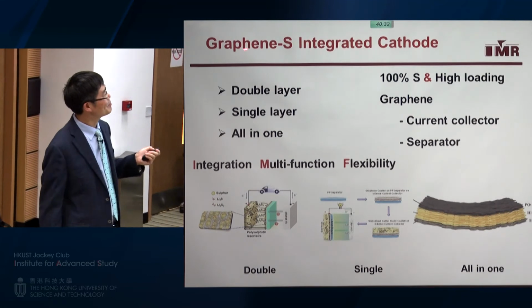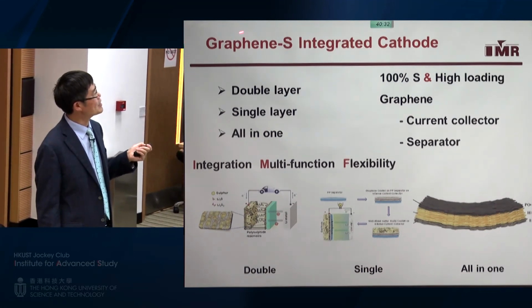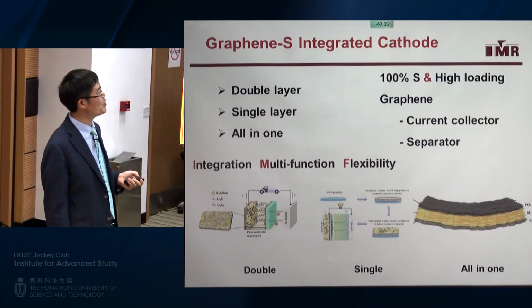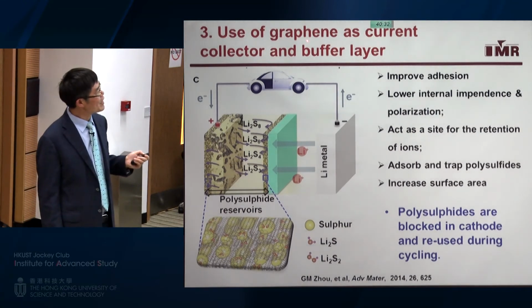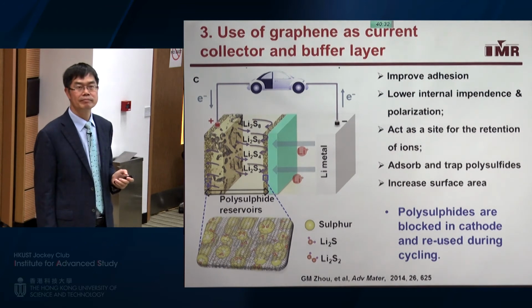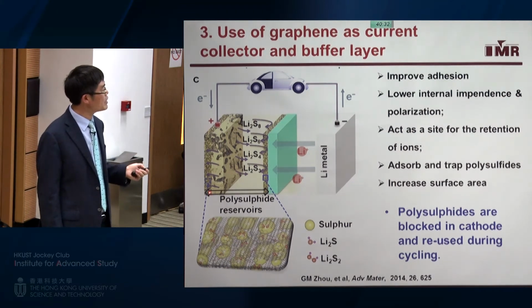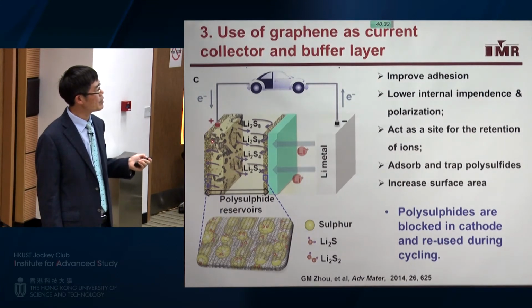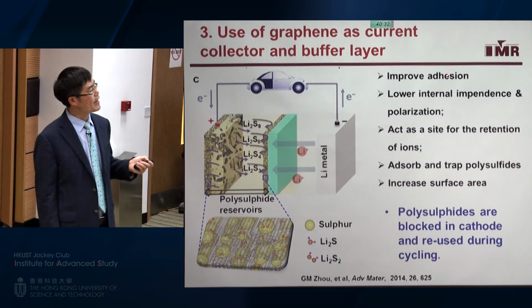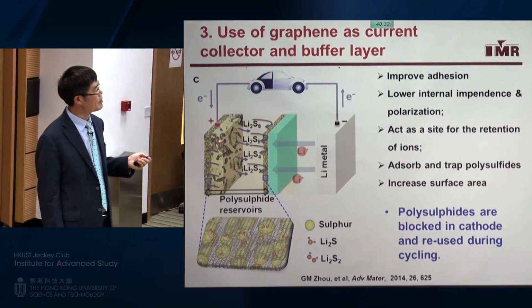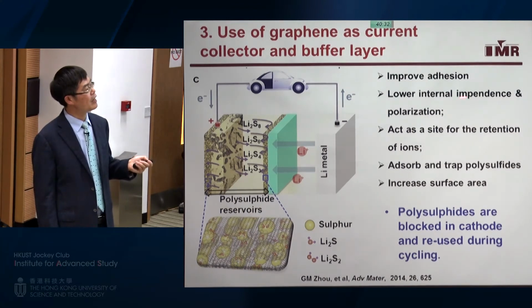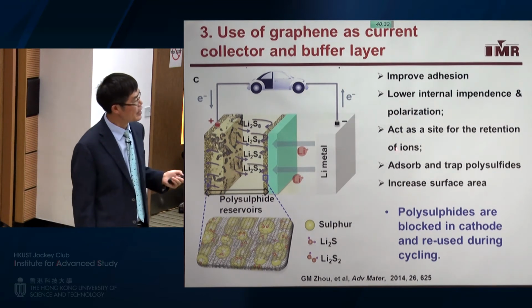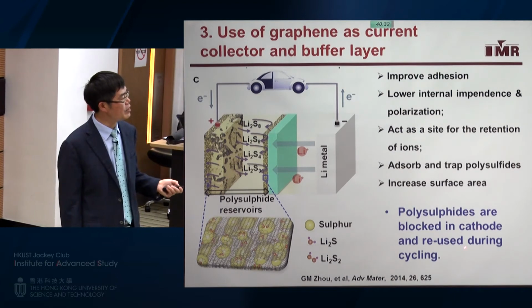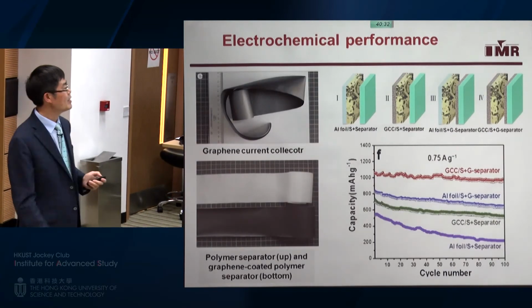Here I show you some easy way. We just want to integrate graphene and sulfur together into some kind of configurations. The first configuration is we try to use graphene as current collector and buffer layer. For lithium sulfur battery, we also need to use a current collector, as I show you here. So here we change the metal current collector into graphene. And also we have a buffer layer on the separator to improve the adhesion between the graphene and the active sulfur material, and also lower internal impedance and polarization. But most importantly, to adsorb and trap polysulfide, which can be reused during cycling. So that's very important.